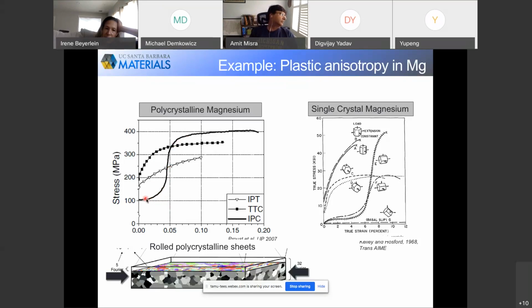What's interesting is that it's not that the twin volume fraction increases steadily and that's why this is coming about. A lot of it is that the twin volume fraction may even increase and saturate at this point, but then this hardening comes about because once they've grown to a certain thickness, you induce a harder slip mode.